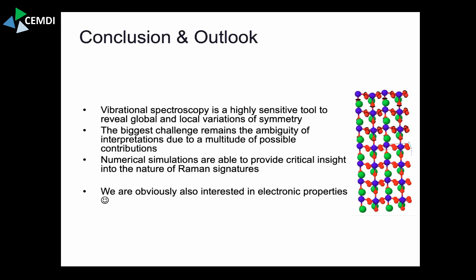There is always a number of candidates that could make an effect, and very often we need a numerical backup to know, okay, if this is an oxygen vacancy, for example, where would the optical signature of an oxygen vacancy appear? What would be the mode, or the modes, associated to the presence of oxygen vacancies, to tell them apart from other effects? So these numerical simulations already gave us some really critical insight, especially for these surface modes. That's why I chose the picture.